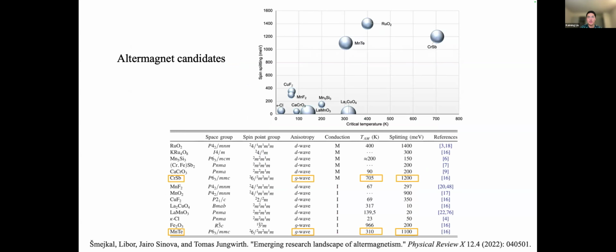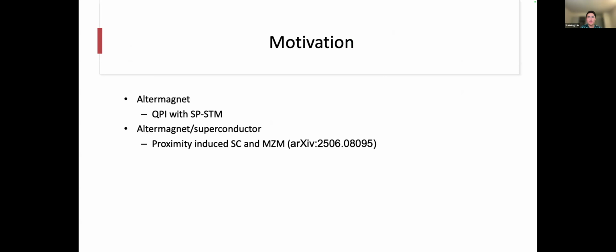So in our lab, we focus on chromium antimony and manganese telluride since they have much larger spin splitting, which makes it easier for us to observe the phenomena in the experiment. So we have two motivations for this altermagnet system. The first motivation is to study the spin polarized QPI signatures in altermagnets with spin polarized STM. And the second motivation is to explore proximity-induced superconductivity and potential Majorana modes at the interface between altermagnets and the superconductor.